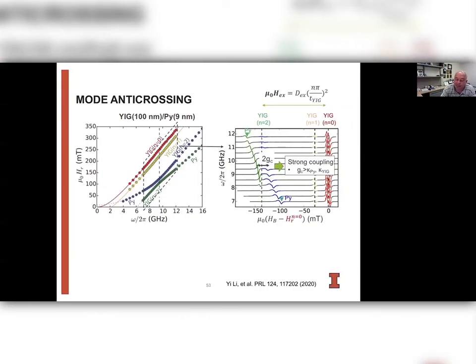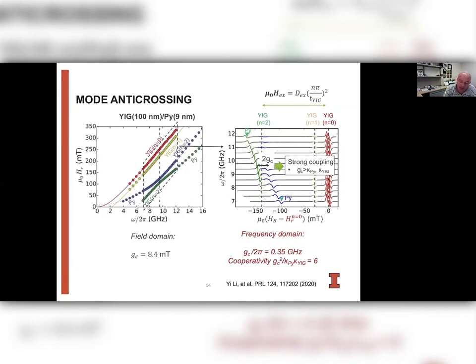Now, again, we can analyze this. We can calculate the coupling from the splitting of these modes, and we can compare it to the individual line widths that we get far away from the coupled regime. And so if we analyze it carefully, we get about 350 megahertz coupling in the frequency domain, which corresponds to 8.4 millitesla in the field domain. And using the measured line widths far away from the crossover, we get a cooperativity of about 6, showing again that we're in the strong coupling regime.